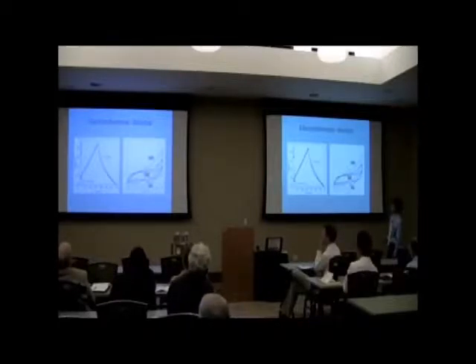And this is the cyclic voltammetry test. This one uses a very small scanning rate, and it looks not very good for this CV curve. And when we increase the scanning rate, it shows much worse than at the small scanning rate.